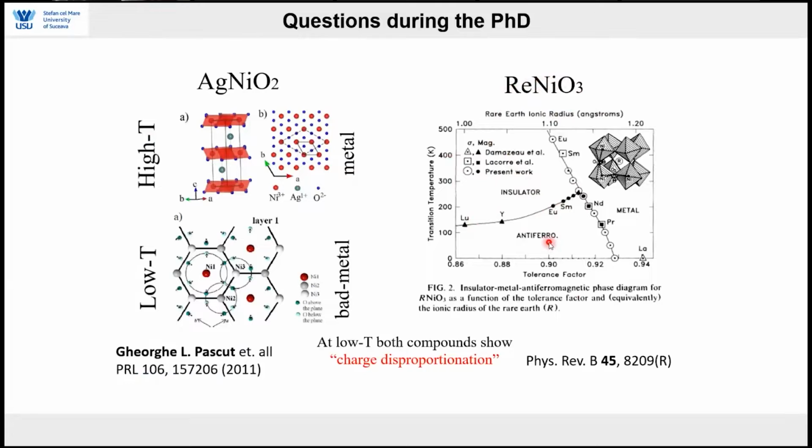You lower the temperature even farther, you end up with an insulating state where the magnetic moments are orderly. But the particular thing about the metal to insulator transition is the fact that your environment changes: once you go from metallic to insulating, one octahedra expands and one contracts.